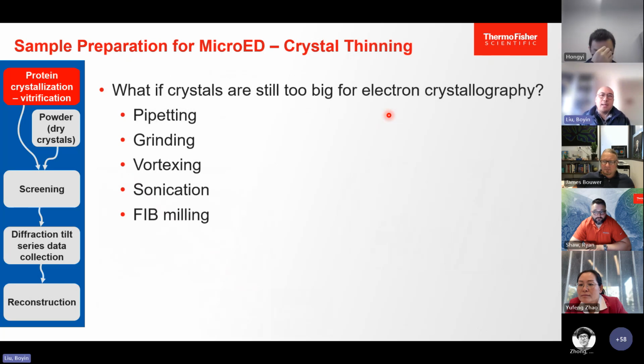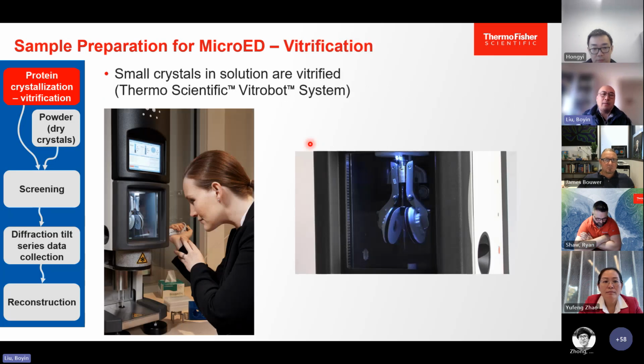When the crystal is too big, there are a couple of methods you can use to downscale the crystals. We've already talked about those. You could do vigorous pipetting to grind, vortexing, or sonication. The first four methods are pretty straightforward, so I'm going to spend some time on the cryo-FIB milling part to give you some details about how to do this. But before I talk about FIB milling, we'll go to sample vitrification first, because you still need to freeze your sample before the cryo-FIB milling part.